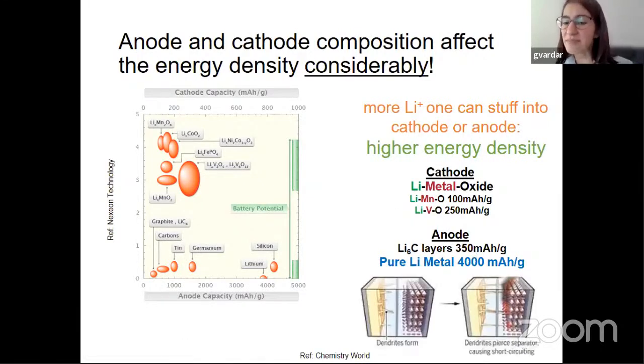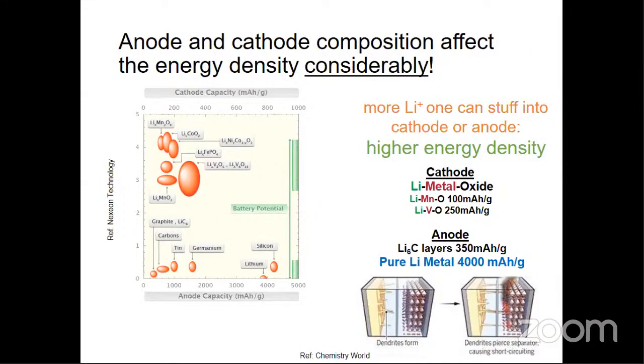But the problem with lithium metal is that it forms these dendrites. These dendrites are basically protruding lithium structures. If these dendrites touch the other electrode, the flammable electrolyte catches flame, so it creates a fire.